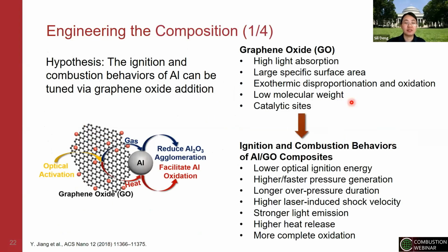So we engineered the mixing, we engineered the interface. How about we use some of the knowledge of doping or bringing additives to the energetic materials and try to enhance the ignition and combustion performance of aluminum. So here I'm going to show you our first attempt on bringing the 2D materials, graphene oxide, into the game. So nowadays there's a lot of research on the carbon-based 2D materials. And specifically, we chose the graphene oxide because it will have a high light absorption so that we have this potential of optically ignite our energetic materials.